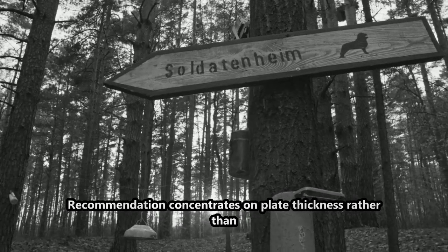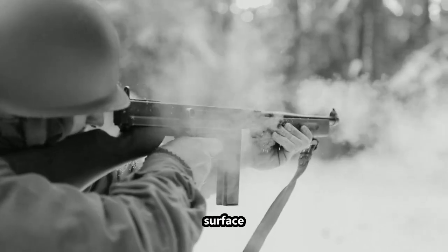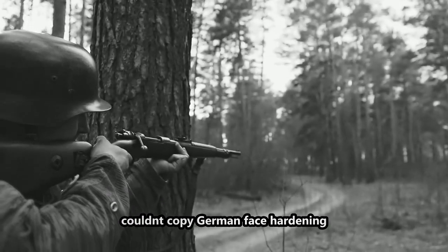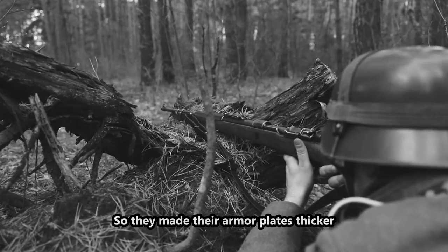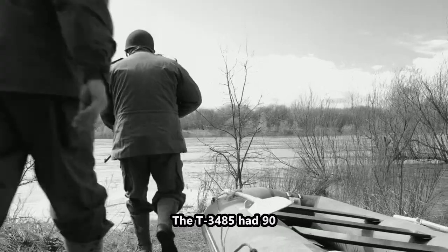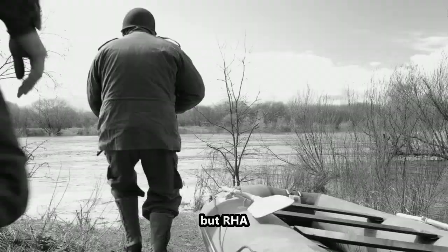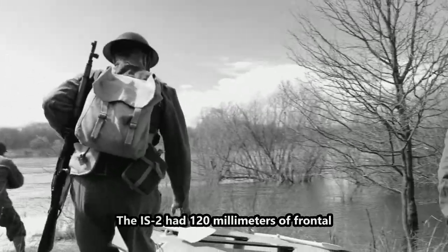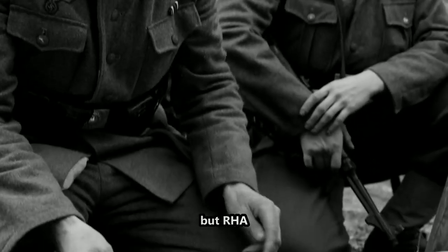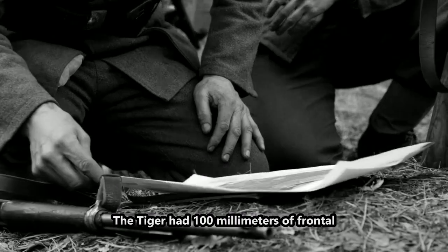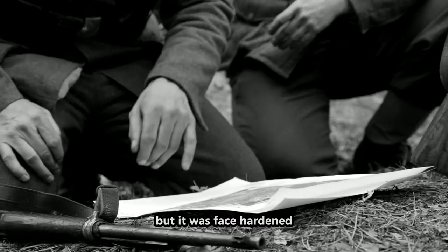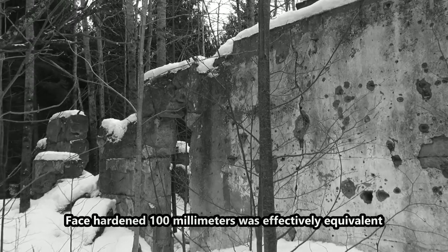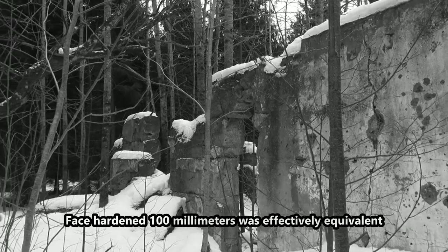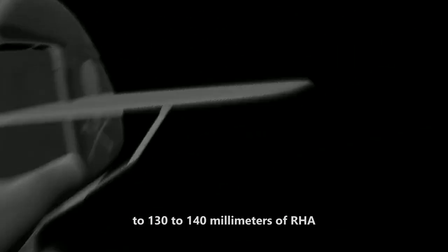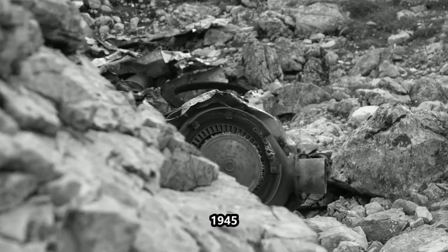This is critical to understand. The Soviets couldn't copy German face hardening, so they made their armor plates thicker. The T-34-85 had 90 millimeters of frontal armor, but RHA. The IS-2 had 120 millimeters of frontal armor, but RHA. The Tiger had 100 millimeters of frontal armor, but it was face-hardened. The physics were simple. Face-hardened 100 millimeters was effectively equivalent to 130 to 140 millimeters of RHA against kinetic penetrators.